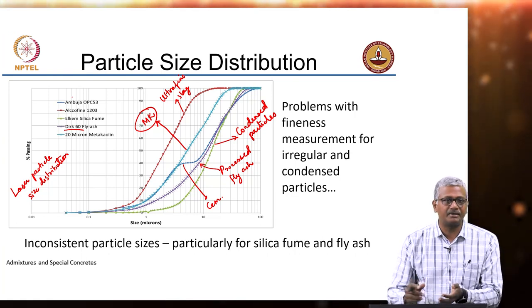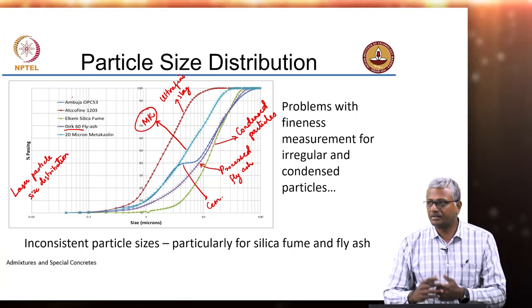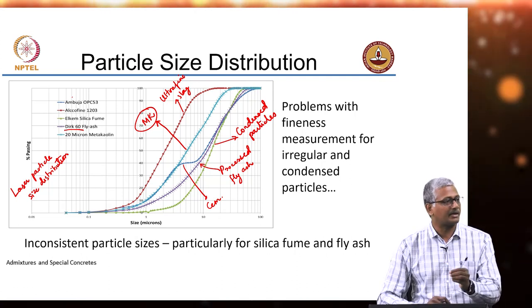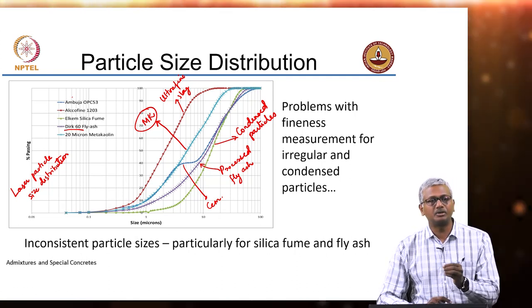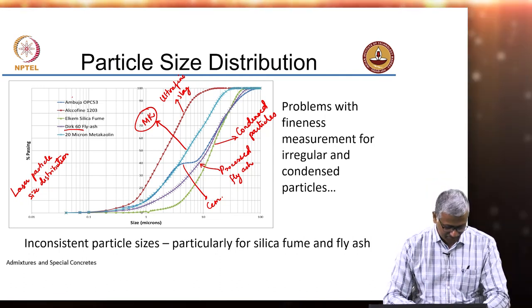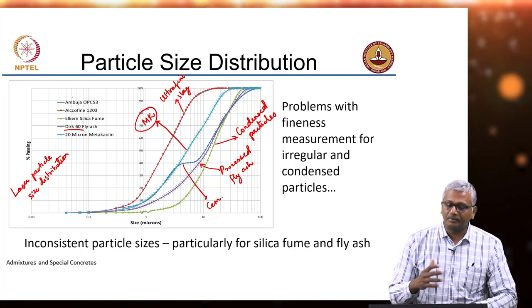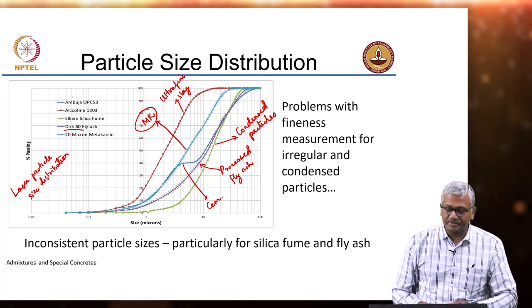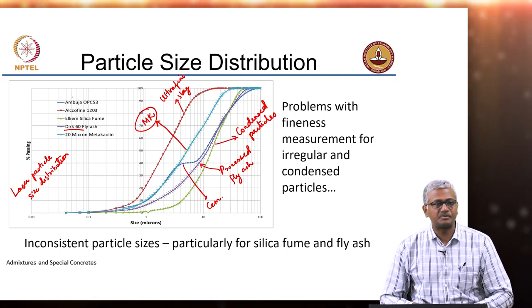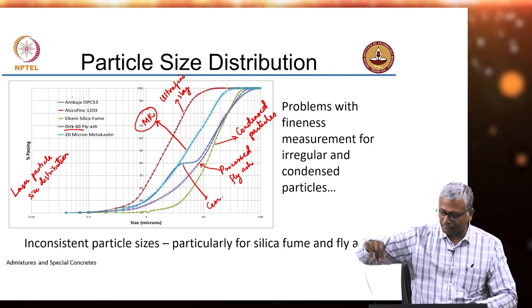That is the most difficult part about doing laser diffraction on condensed silica fume — there is no way to accurately disperse or get the individual fine particles of silica out for a test of this nature. We tried all kinds of things, including mixing it with sand and then sieving out the sand, but it produced many difficulties in extracting the small silica grains without the mixing action given by the aggregates. These and several other difficulties with measurements will be discussed in the subsequent lectures. We will stop with that for today, thank you.